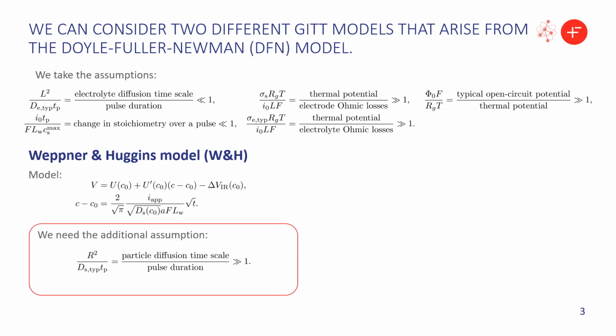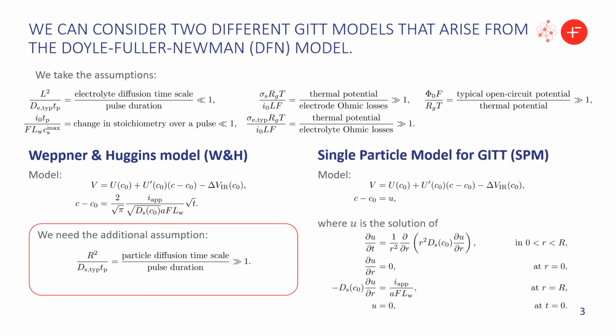And actually we find out that the Weppner and Huggins model is one of the outcomes we can get if we additionally assume that the particle diffusion timescale is larger than the pulse duration. That assumption is very common in all the literature when these types of models are used. And in fact, that's what allows us to get this expression for the variation in the concentration, C minus C naught, that behaves like a square root of time. That's where it comes from.